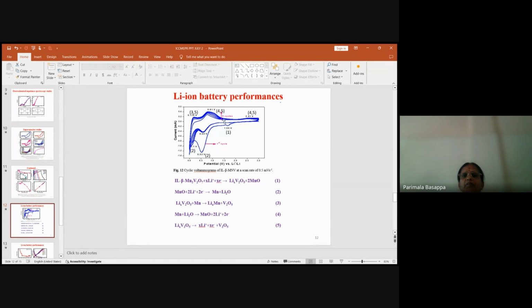Okay, and two peaks we can see here. This is 2.61 volts and 0.176 volts. In between these two, a broad peak is obtained at 0.81 volts. This is mainly due to the delithiation process as per equations 4 and 5. Then equation 2, 0.53 volts, is where the manganese metal is obtained. So 0.53 volts is attributed to the solid electrolyte interface formation along with the entire lithium ions being taken up. So these equations 1, 2, 3, 5 show how the lithiation and delithiation process takes place in this.